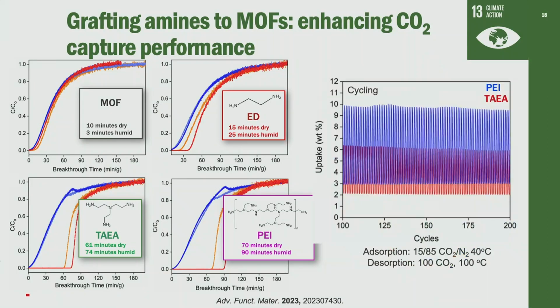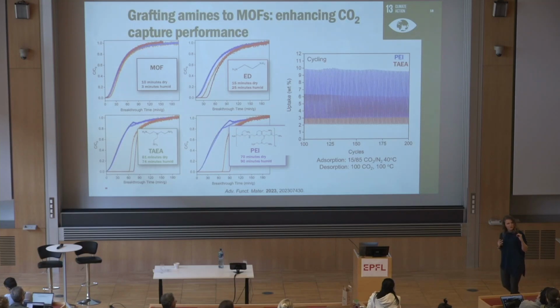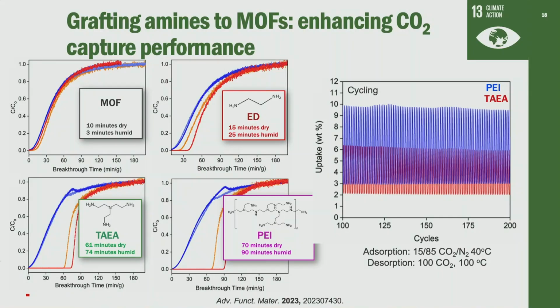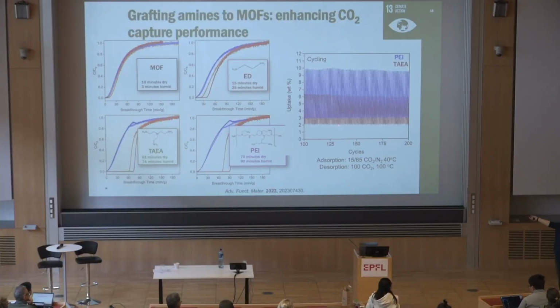Now we want to see if the material cycles. So what we've done is we do the adsorption process for the CO2, 40 degrees Celsius. Then we heat that material up to around 100 to 120 degrees Celsius, and we release that CO2. So what you're seeing is weight gain because the CO2 is going in, weight loss because the CO2 is coming out, as we swing the temperature back and forth. And so what you're seeing are cycles. We've cycled these up to 200 times in dry conditions, and we've done over 1,000 times so far, which is about 2 months of cycling under wet conditions. And the materials perform extremely well.